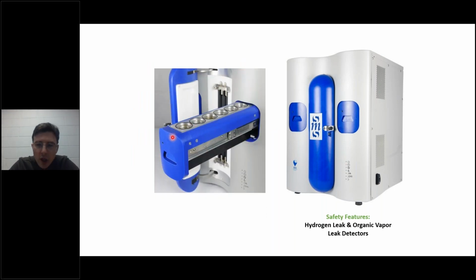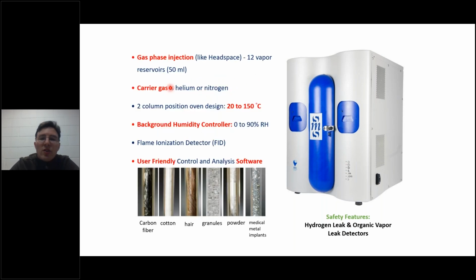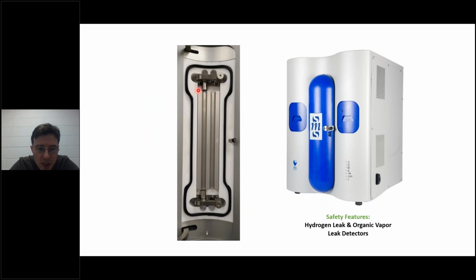Now, how we introduce our probes is that from the saturated headspace of these probes, we make a gas injection. So a little tube will go into the top of this reservoir. We will flow out from the saturated headspace, and then those probes will be diluted with our carrier gas. And that in this case will be helium or nitrogen. So what this will do, this will introduce these probes from the top of this column. So at the very top of the oven, we would have our sample packed in the middle here, and then from the end here, it would pipe our probe molecules into a detector, which would be a flame ionization detector. And then we can measure the amounts and the time taken for our probes to elute through our column.